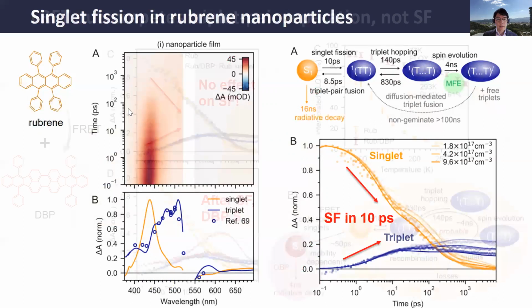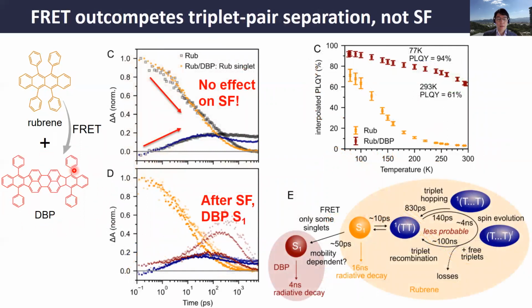Then we add the third component collector, the DBP. Here, surprisingly, we observed almost no effect on the singlet fission dynamics. After singlet fission, DBP singlet was observed. Singlet fission dynamics was not affected, so it still happens at 10 picoseconds. And after that, the FRET with a time constant of 50 picoseconds happened. So singlet fission is too fast, so FRET cannot outcompete. But still, this third component, the DBP collector, can improve the fluorescence quantum yield.